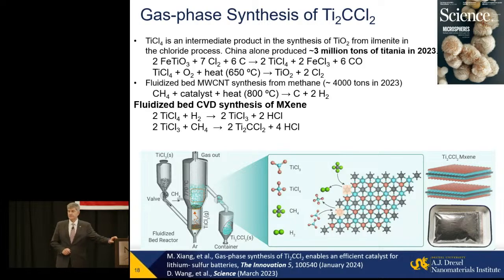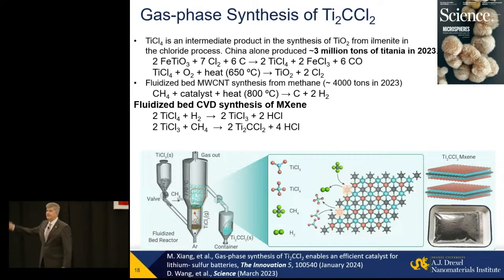What is important? All the white paint you see on the walls and the ceiling is titanium. Titanium dioxide was produced, 3 million tons just in China alone in 2023, by the so-known chloride method, taking ilmenite, iron titanate, treating with chlorine and carbon, and after that oxidizing titanium chloride with oxygen, producing titanium dioxide. Titanium tetrachloride is an intermediate product for this synthesis, with a cost which is very minuscule.